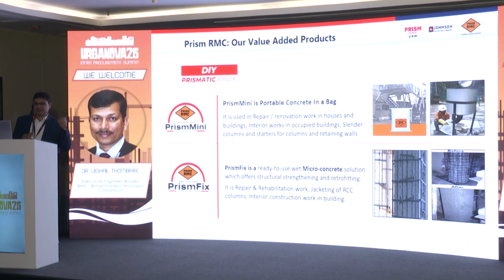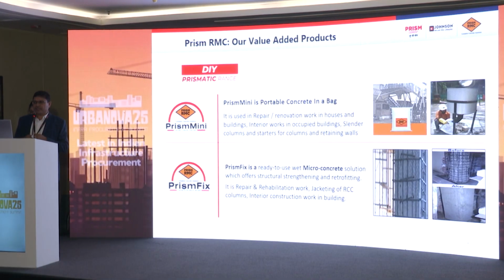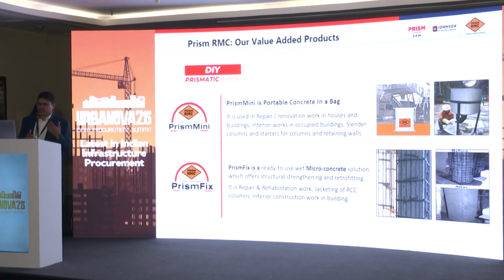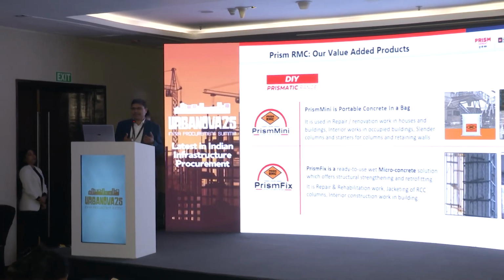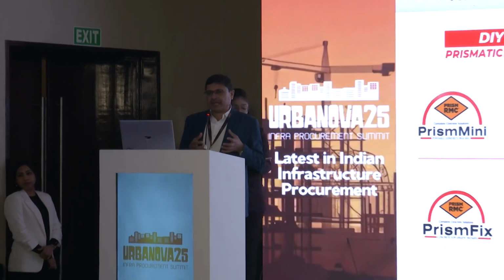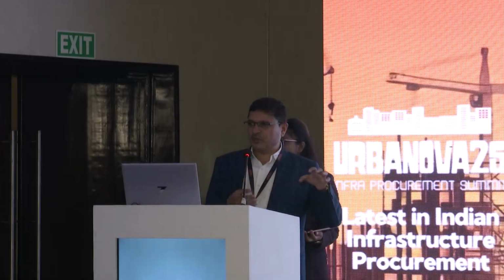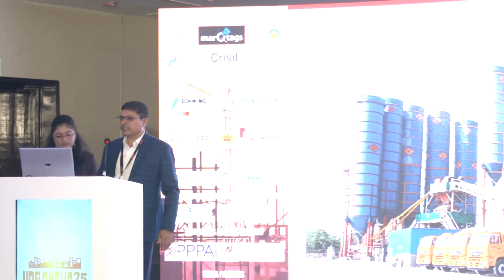The second product is Prism Fix, which is a non-shrink wet micro concrete, also supplied in 30 kg bags, and it is ready to use. Dry micro concrete is available in the market, but for column strengthening or repair work, it is quite difficult to maintain the required water cement ratio or mix this micro concrete at site. That's why we found one solution which is very helpful for our construction industry. Here are some job site photographs we already did. Thank you very much.